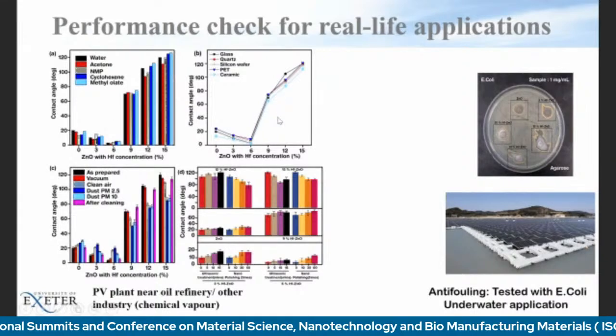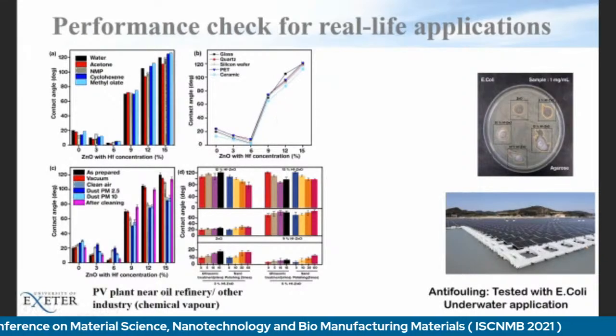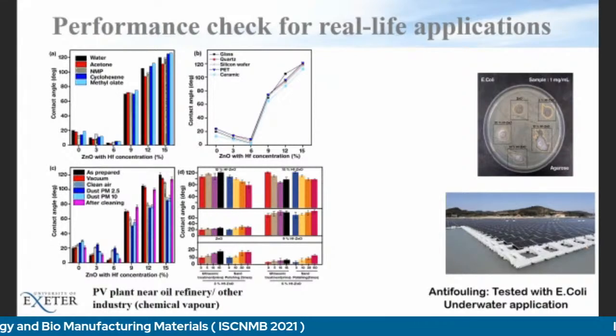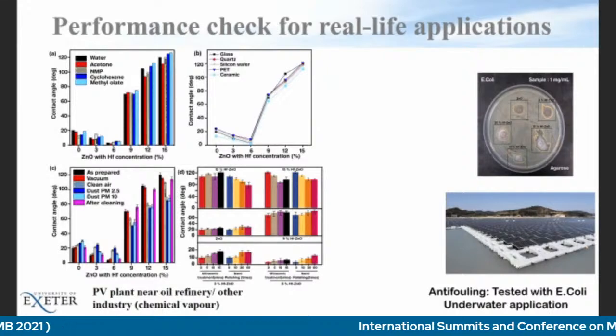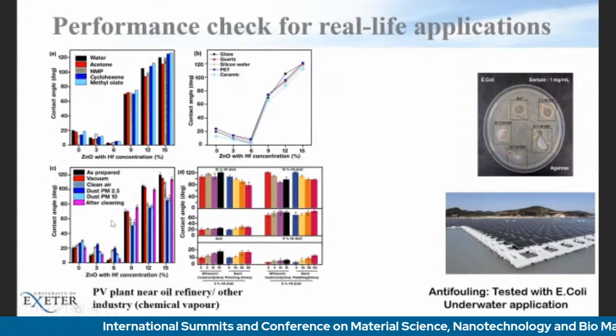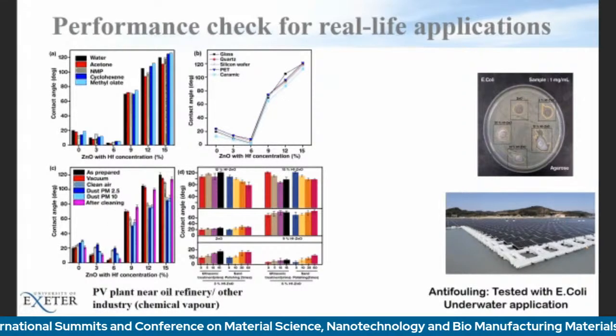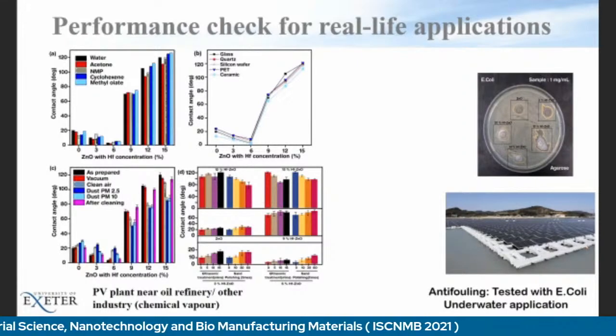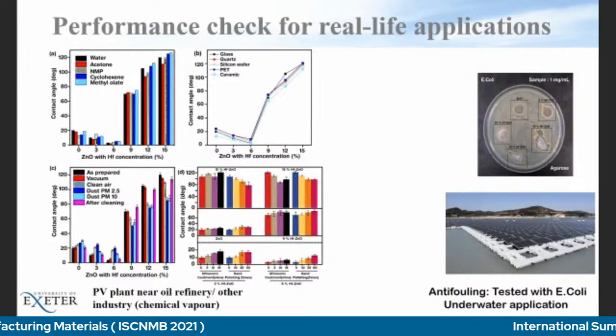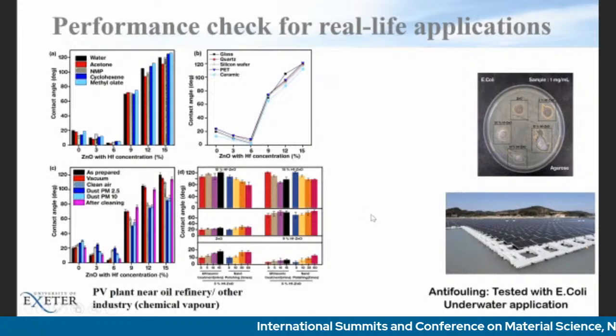Also, we wanted to investigate what happens if we don't use the glass substrate but other substrates like quartz, silicon wafer, ceramic or PET, how this material will work, and we found very similar properties to the glass surface. We also checked the enhanced properties, so we kept this material under dust PM 2.5, dust PM 10, and also clean air and vacuum. We found that the properties didn't change that much after this testing.